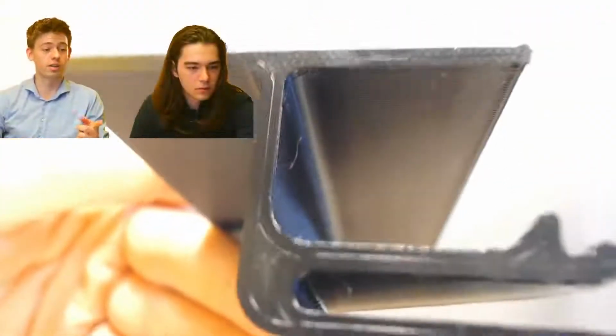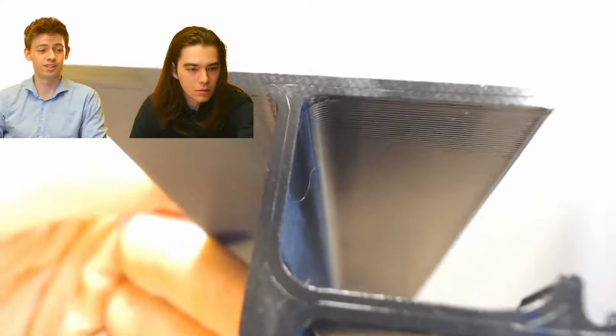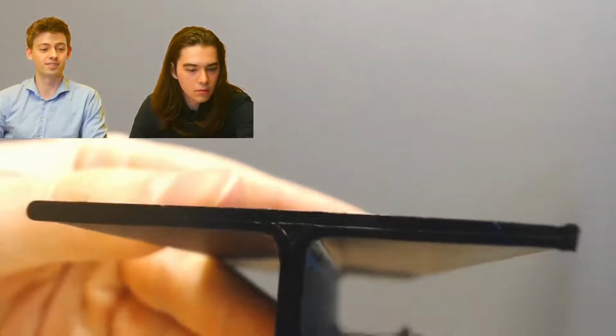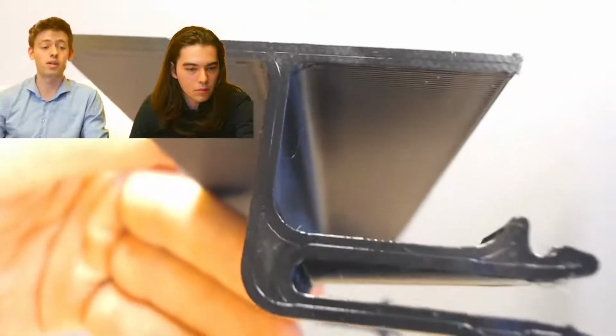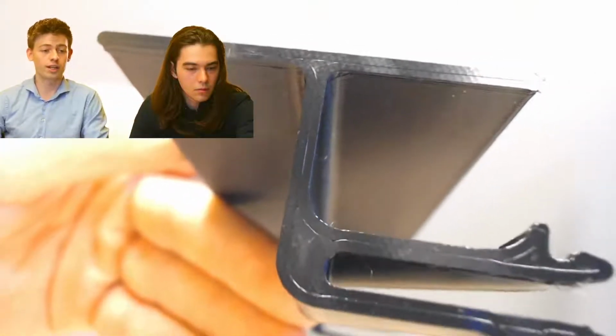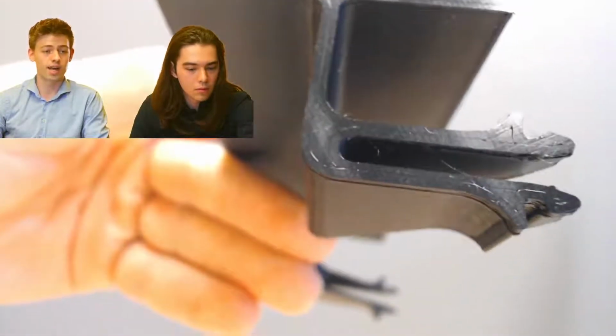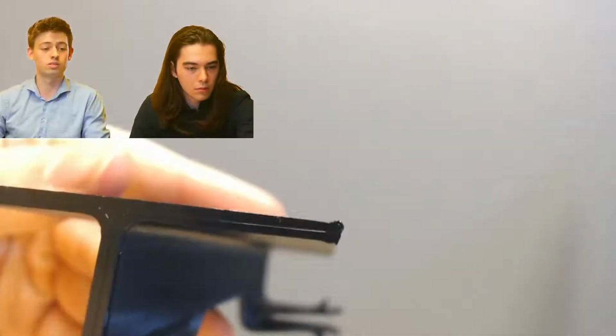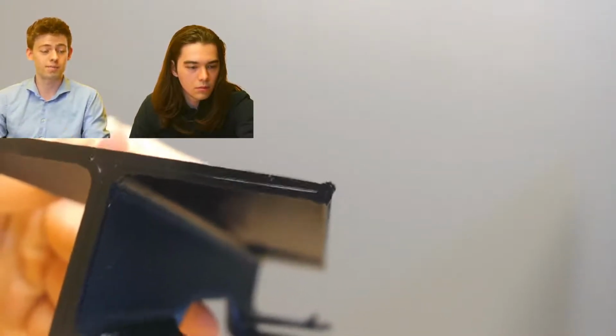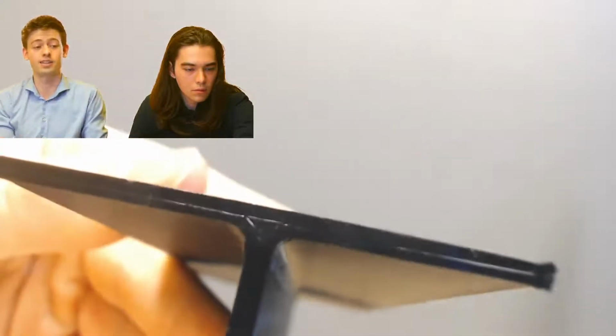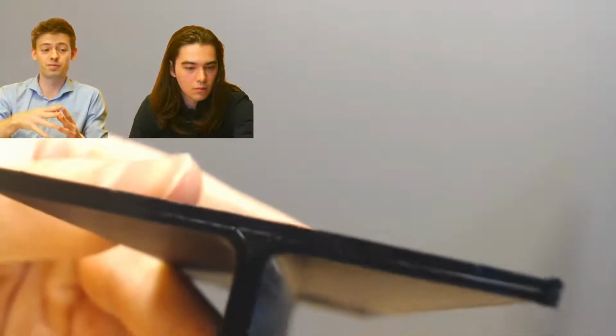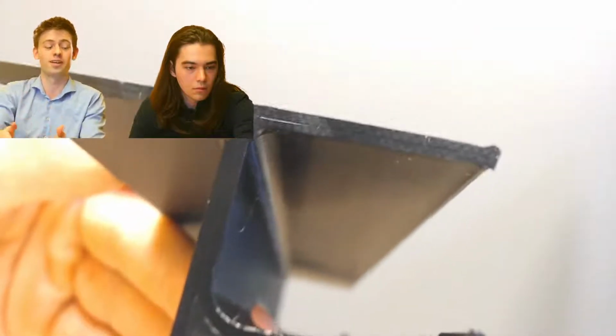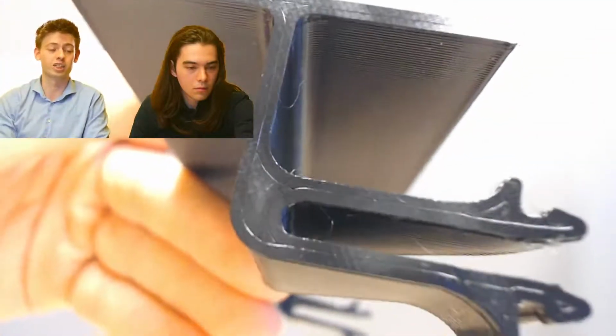So here's actually a really good part, a great example of first layer speed being a really important factor, and I guess line width as well. But you can see these really sharp direction changes on the top part of this ramp, and with any normal print settings, like the default Cura settings, I doubt that it would actually be able to properly print this thing because it's trying to print this maybe at a slightly faster speed, but also with really thin extrusion lines, and there might not be enough heat energy to keep the materials liquid for long enough. I think it'll actually peel up when it does that direction change.